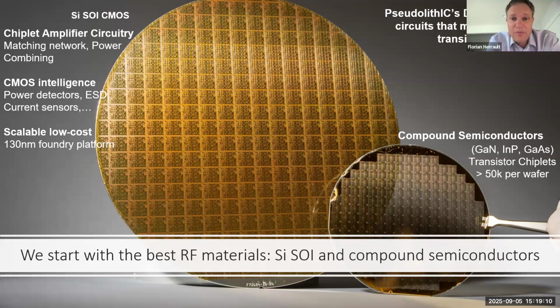And then we do this on a scalable, high-volume commercial platform. We use a 130 nanometer RF SOI platform today, or a passive high resistivity silicon interposer. Those are very low cost compared to high-end RF silicon or compound semiconductor. So we're able to tape out very frequently, effectively every other month, or sometimes quicker, in our silicon platforms to iterate or develop new circuits in the same wafer. That's really our design IP.